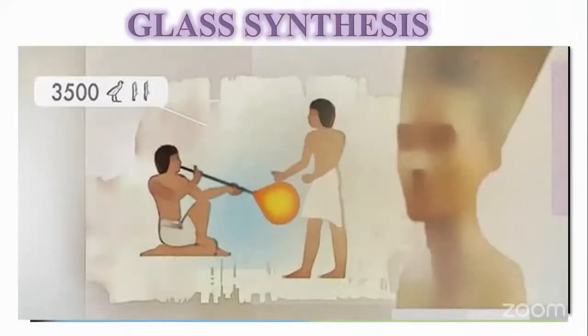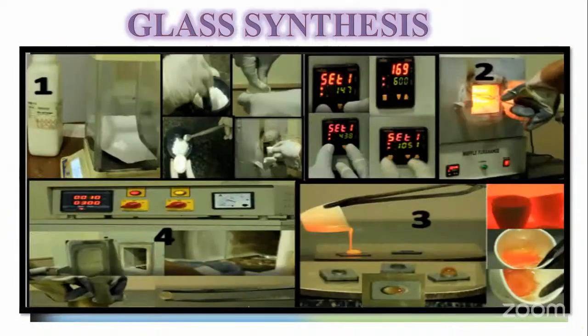So now, if I have to take you back to 3500 BC, the traditional way of formation of glass was by blowing the sand, and that's how they used to make the glass. But today, in modern day, how do we prepare glass, particularly in lab scale, if I have to tell you, we try to weigh the sample, and then we try to have a batch matrix, and then we try to pulverize it. We ensure that the amorphosity is being maintained, and we transfer it into a crucible, and we place it inside the muffle furnace. Once it is being placed inside the muffle furnace, it is not advisable or recommended to quench directly at the melting temperature.